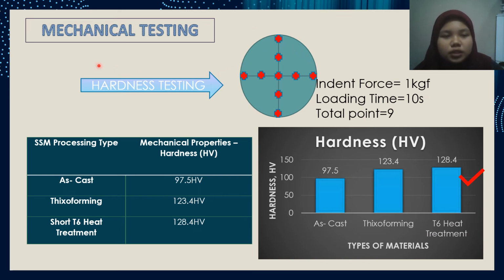So for the mechanical testing, hardness testing, I used an indentation force of 1 kgf and a loading time of 10 seconds for a total of 9 points, and then these are the average for every 9 points for every sample: as-cast, THIXOFORMED, and short T6 heat treatment.